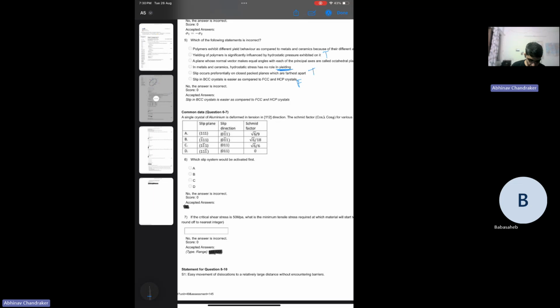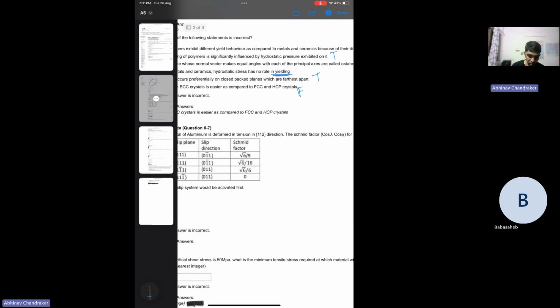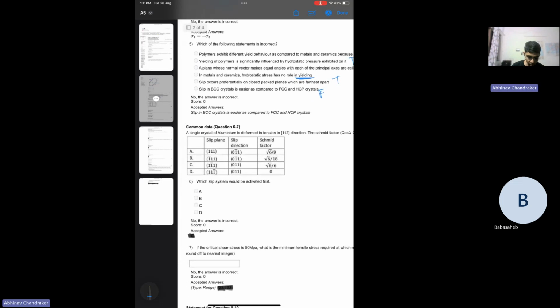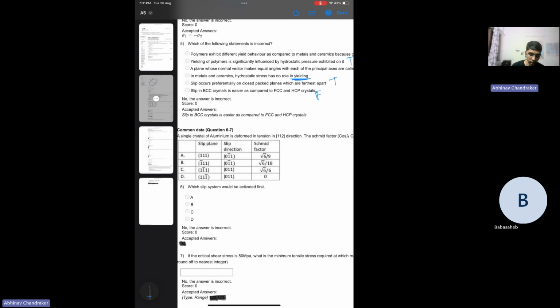If the question was about fracture, then hydrostatic stress would have caused fracture, but yielding is caused only by plastic deformation. So yielding basically means that plasticity has started. It's the onset of plasticity. So in plastic deformation, we know hydrostatic stress plays no role in case of